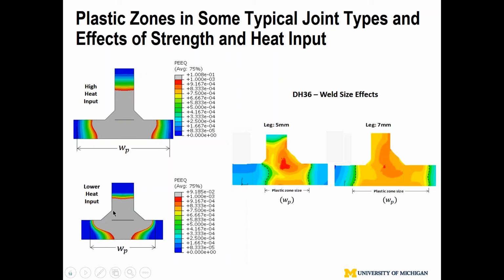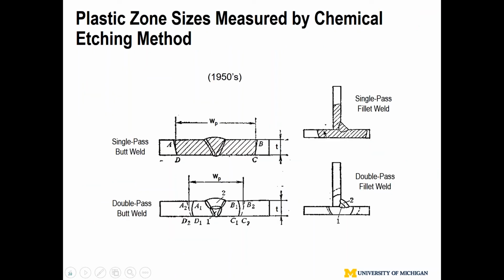So that's the key message. That's simulated by a finite element model. WP is the width of the plastic zone multiplied by thickness. That gives me a plastic zone area AP or A2, and with unit thickness, we call it WP. The reason I'm spending a bit more time on the plastic zone is that it is the fundamental quantity impacting distortion. This NASA example is related to Space Shuttle Station construction, the 2195 tank, so I'm going to bypass that. The plastic zone is a fundamental quantity we can work with to develop a distortion control strategy. In that case, why is low heat input beneficial?